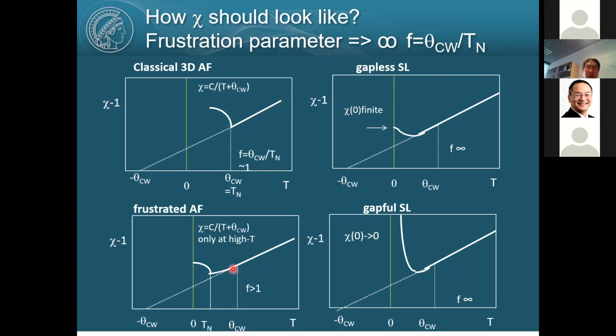But if frustration works, this long-range ordering is suppressed, and it takes place at a much lower temperature than the Curie-Weiss temperature. So you can view the ratio of the Curie-Weiss temperature to the Néel ordering temperature as a measure of frustration. If frustration is stronger, this ratio goes up. In a quantum spin liquid there is no Néel ordering, so this frustration factor is infinite: you see Curie-Weiss behavior, but you don't see any magnetic ordering.